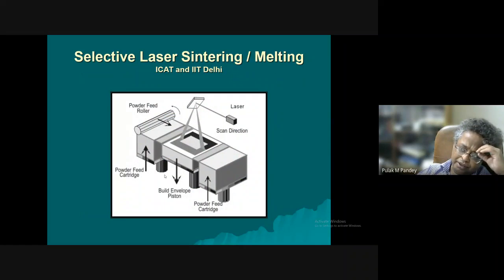Then laser sintering, when we talk about it, is a powder bed kind of system. Here we spread the powder through this recoater, and again there is a laser and a galvano mirror, and the laser spot moves. Wherever the laser spot goes, the fine powder gets melted from its periphery, and they get entangled, or rather they form a lump. It is very much unlike the basic concept of powder metallurgy, where we study sintering. You should not get confused that there is any application of pressure or compacting or taking it to the furnace. No, it is a pressureless spreading of the powder, and when the laser spot comes, it gets melted at the periphery and connected to the neighboring particles. That's how the solid lump is formed.